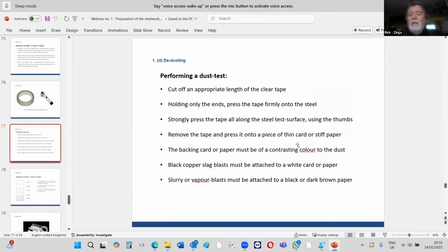So that's what's showing you here. When you remove the tape, you put it onto a backing card. For example, if you're blasting with copper slag, your backing card would be white, because when you put your tape onto the card and check it, you have a good contrast in color.